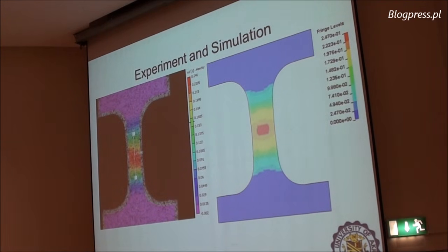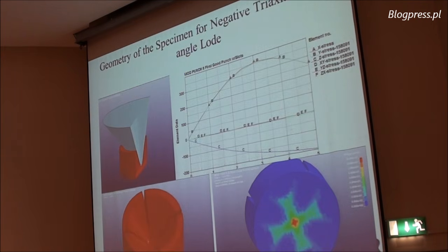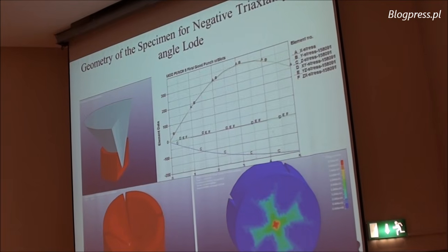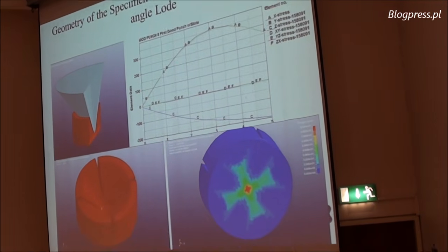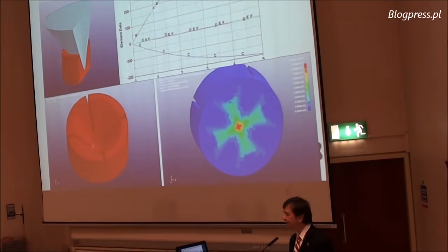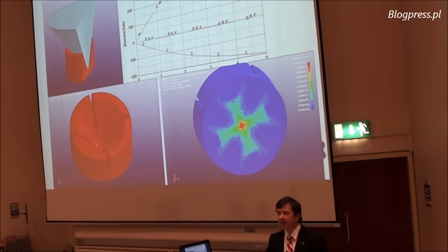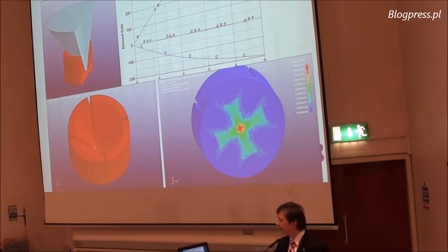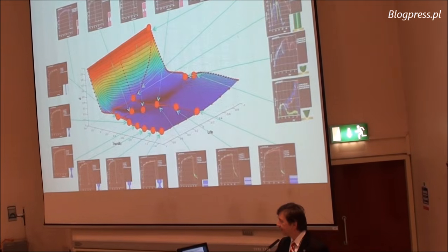And we can again observe experimentally, and we developed a special specimen. This is a special specimen that is a punch, and that punch expands the size of the specimen, at the same time pushing the bottom and therefore producing the three-dimensional state of stress at the bottom, tension in X and Y, and compression through the thickness. So this is the negative so-called Lode parameter or Lode angle and negative triaxiality.